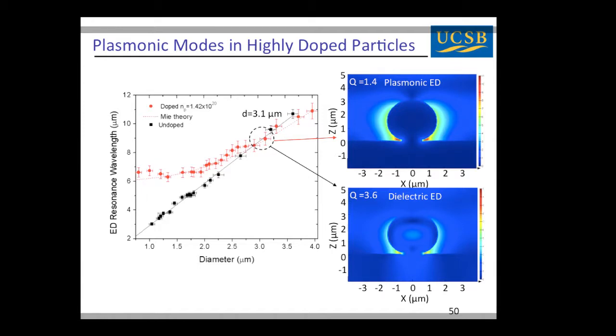What I'm showing in this plot is the location of an electric dipole resonance as a function of size. We have an electric dipole mode when the refractive index is positive, when the particle is undoped, so we see large field intensity inside the sphere. And at high doping levels, on the order of 10 to the 20, we see a similar electric dipole mode. The radiation patterns are the same, but now the material has a negative epsilon, or permittivity. It behaves like a metal. There's no field internally.